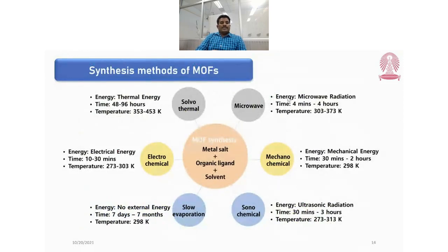A different synthesis method of MOF. First, microwave synthesis. In this method, we use microwave radiation. It will take 4 minutes to 4 hours. Then the mechanochemical method. It's like a ball milling method. Here it takes 30 minutes to 2 hours.